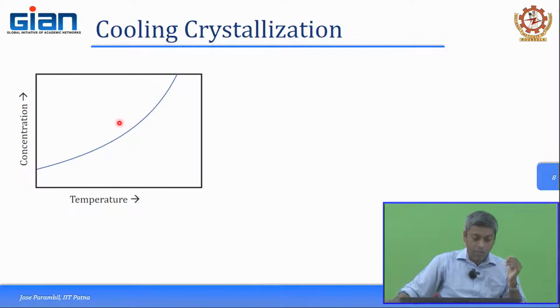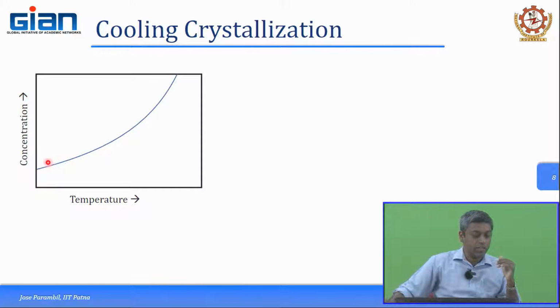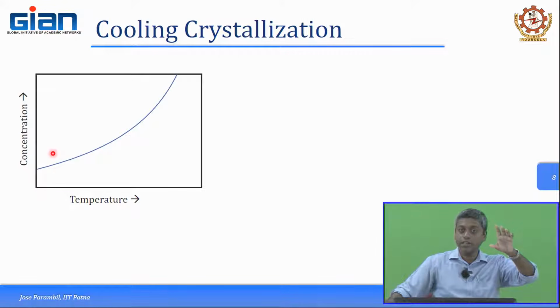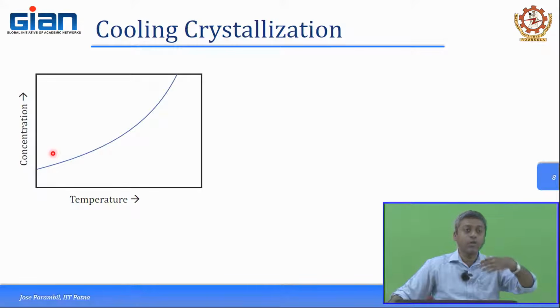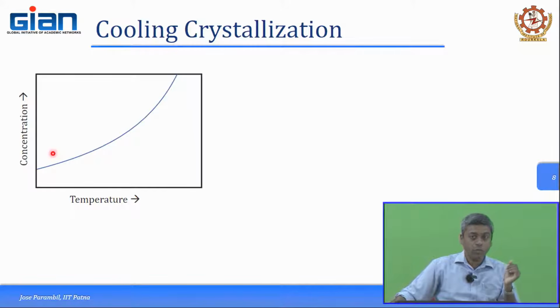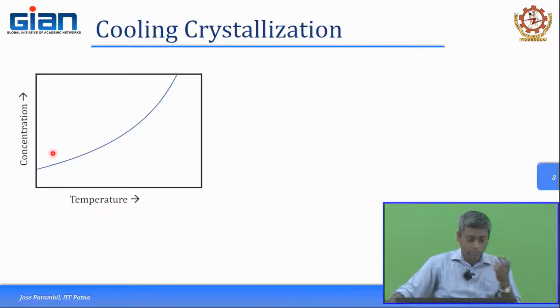So, the concentration would come down and meet with the solubility line, and as you keep on decreasing the temperature, it would follow the solubility line and stop when you stop the temperature cooling process. So, whatever is this concentration difference, you started from let us say this level over here, and you are coming down and cooling it up to this particular level. So, this concentration difference, this vertical difference, that is the concentration of the protein or the material which is now crystallized, and something that you can get as solids.